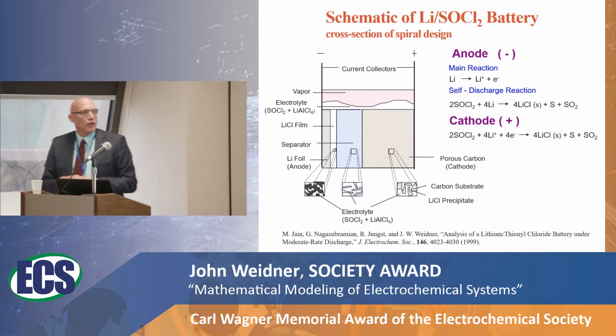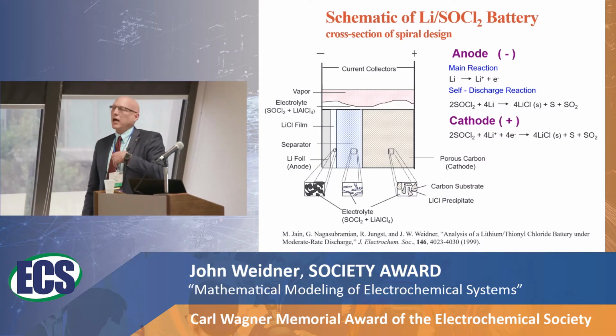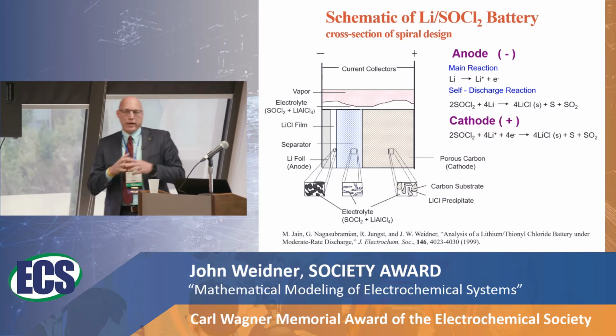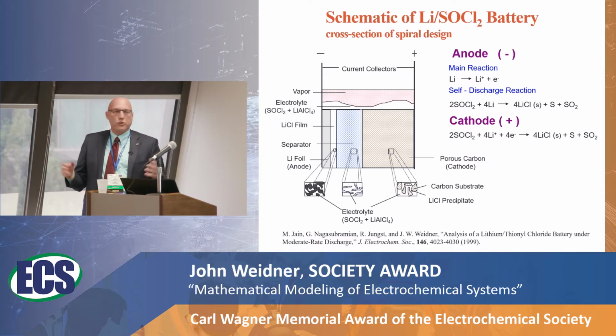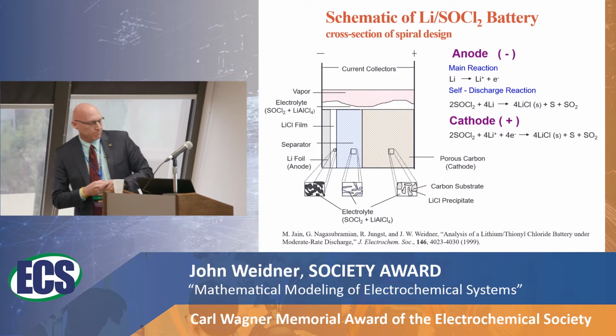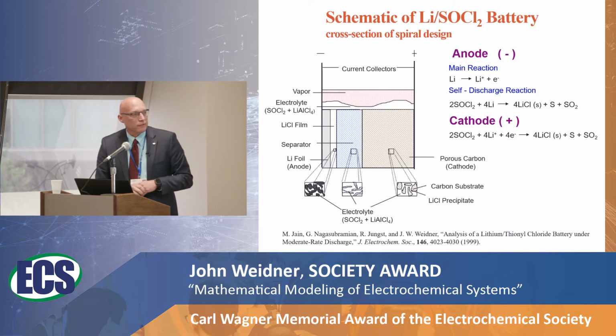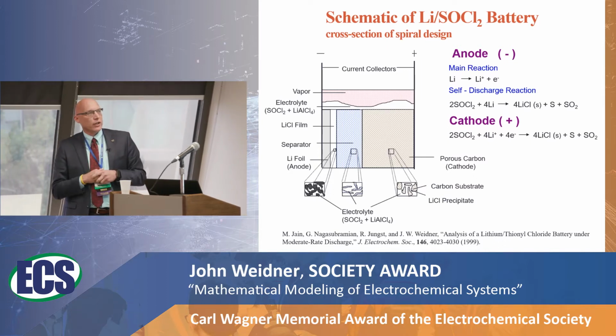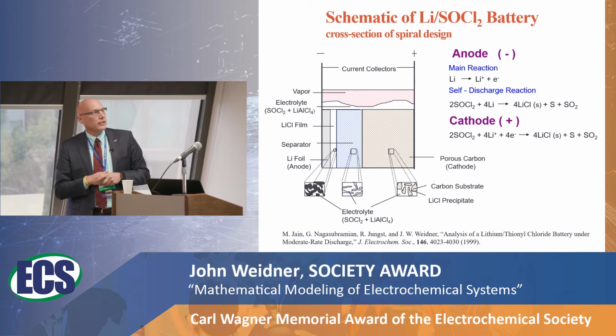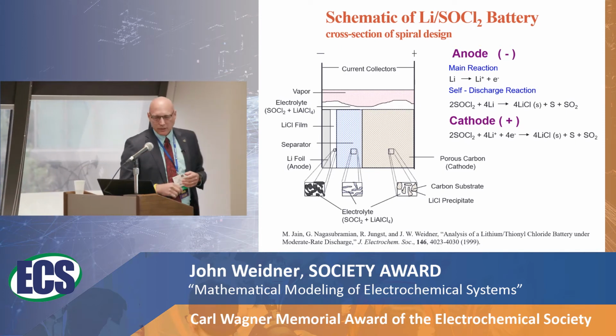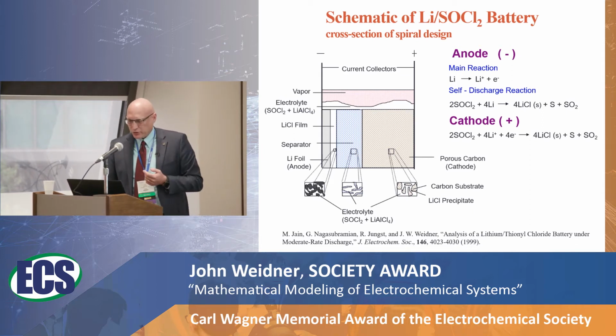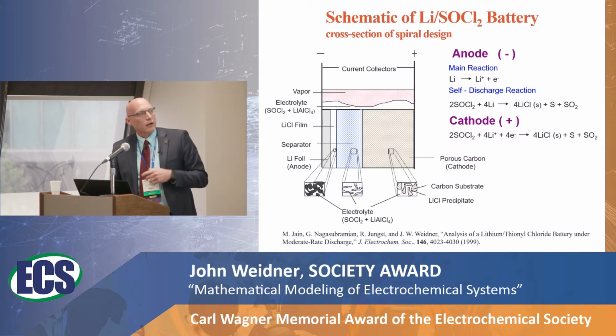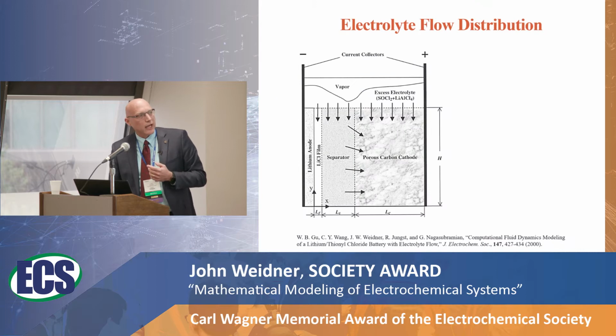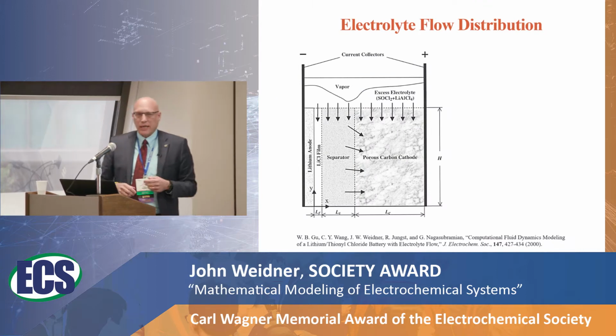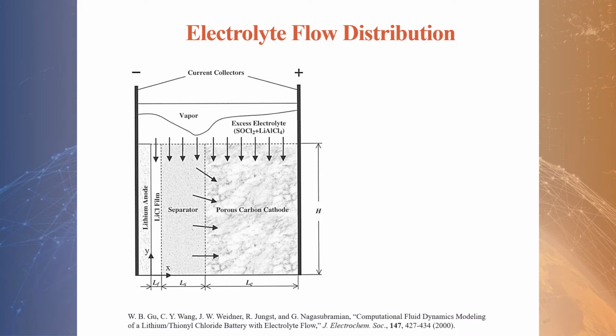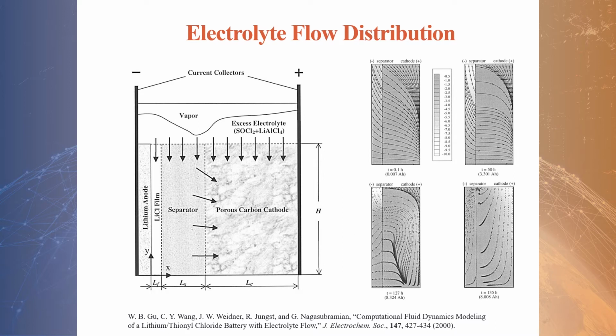So the key thing we were trying to understand is, depending on the rate and operating conditions of temperature and so on, and design, how this reaction distributed throughout this porous electrode. And so we did a series of models on this. It's also very interesting to look at the flow conditions that occur. You've got a headspace that's got some excess liquid material that has to flow through the separator and the porous material, so it becomes a very interesting two-dimensional process, and we did the flow distributions and so on in the cell. So once again, you can get some insight into what's happening inside the cell, which would be almost impossible to visualize otherwise. If you're confident that you've got the physics right, you can look inside and see some interesting things.